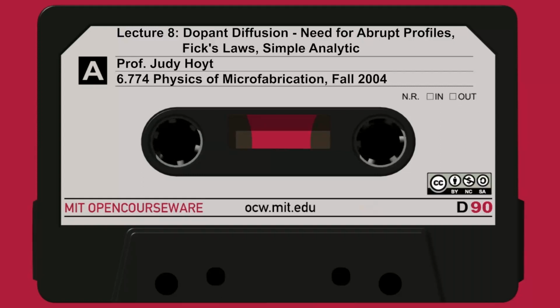So it's the gradient of the flux. That's what we're saying with Fick's second law. Now for the flux F, we can substitute in Fick's first law, F equals minus D partial C by partial x. We substitute that in, and we get the equation in the middle of the slide, which is the differential form of Fick's second law.